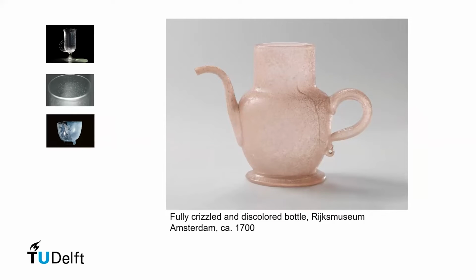Yep. This is another example of crizzling. And when this object was made, it was completely transparent, but also colorless. So the crizzling, the formation of the cracks, also enabled the penetration of oxygen into the glass network, which caused the change in oxidation state of manganese. So that means that manganese was added to decolor the glass originally, but when it changes oxidation state, the manganese itself turns pink. So that's what happened all over the surface of this object. And I will come back later to this object and also demonstrate why it's important that we deal with these kinds of issues.